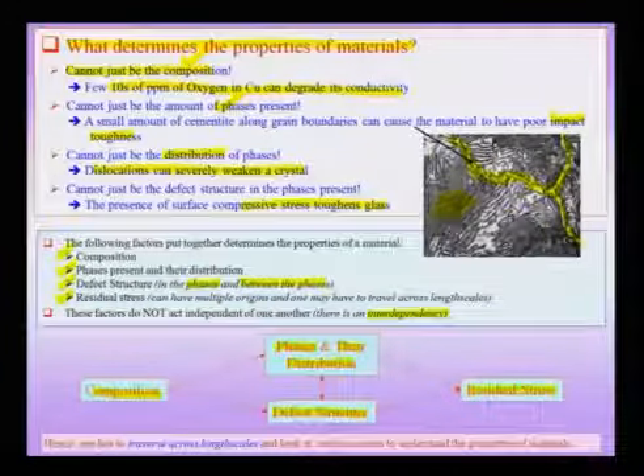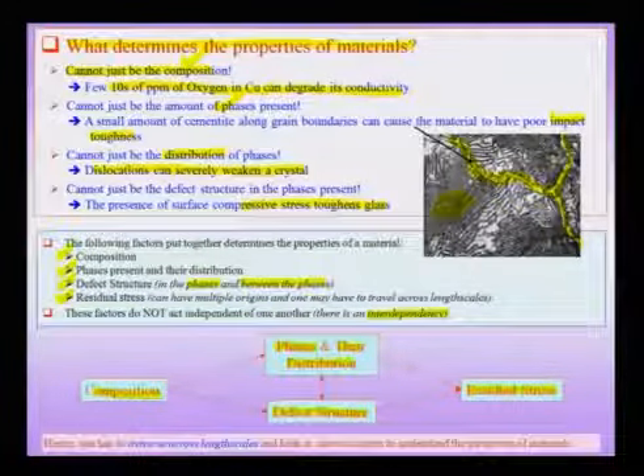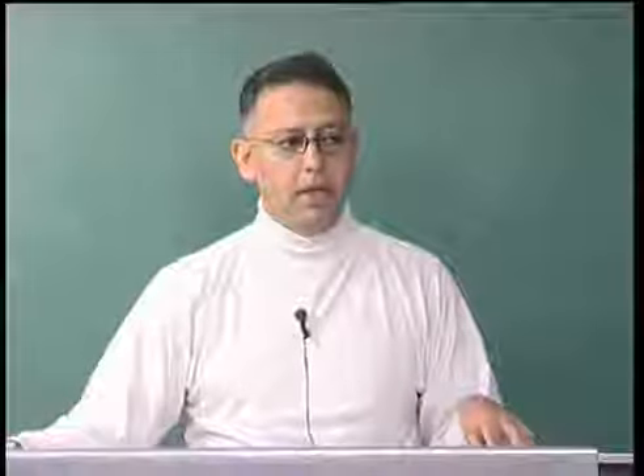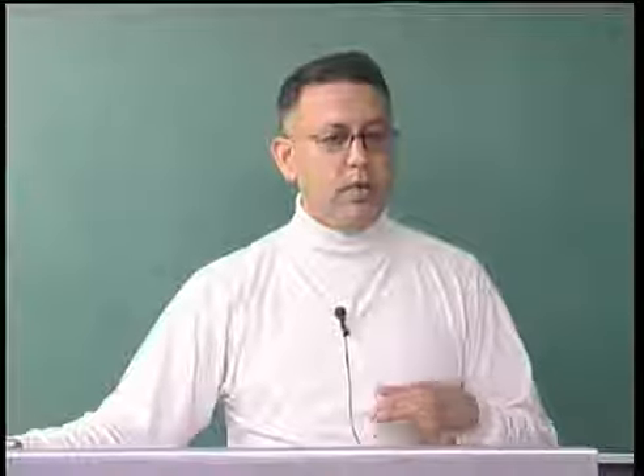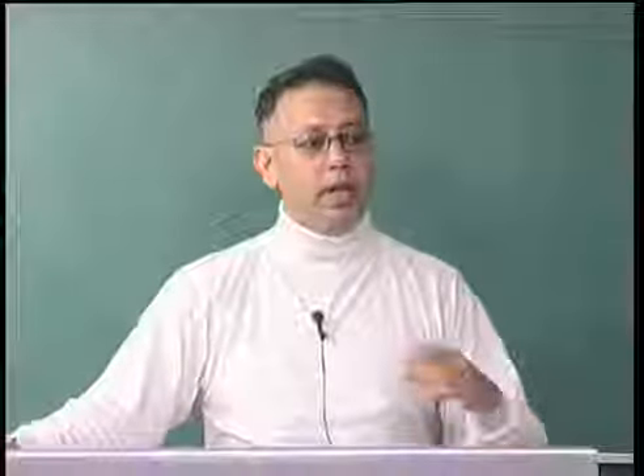We said last but not least that residual stresses play a very important role in the properties of a material. This is often underestimated. In fact, residual stresses can play a very positive role, like we saw in the case of toughened glass, wherein we introduced compressive residual stresses on the surface which give rise to quite a bit of toughening of the glass. But on the other hand, residual stresses can also lead to warpage of the component and therefore can be deleterious, and we may want to avoid residual stresses in many cases. Nevertheless, the presence of residual stresses, which again has to be understood spatially and temporally, that means how the residual stress is distributed within the material and how it is evolving in time, is very, very important for the properties of the material.